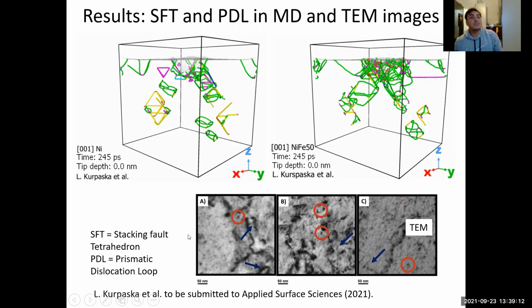So we are talking about these dislocations, these characteristics of the material, but what about the experimentalist researchers? Are they also finding this kind of defects in the material? Yes. So here we have the TEM image that the experimentalists can obtain from the samples. And here they can identify this stacking fault tetrahedron for nickel. This TEM image is for nickel. Here it is. And this is another prismatic dislocation loop, and another prismatic dislocation loop.